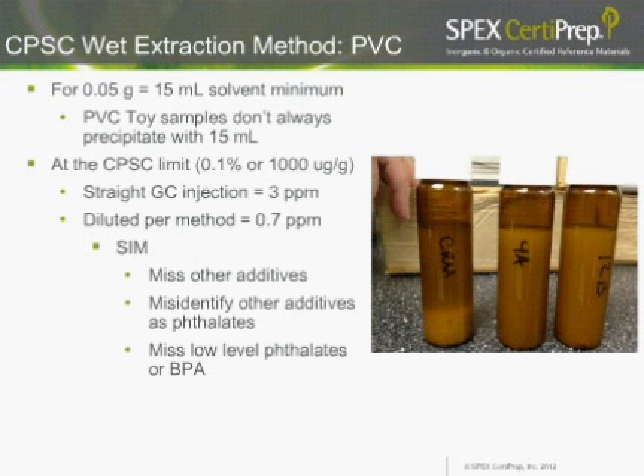We decided to use scan modes because, as I said, we wanted to see, are there any other additives in these plastic toys? Were there any phthalates which potentially could be misidentified as one of the restricted phthalates but was not a restricted phthalate? And what happens if the levels were very low? Would we miss those entirely? Something like a Bisphenol A might be potentially very low, and we would not be able to see this if we use SIM mode.